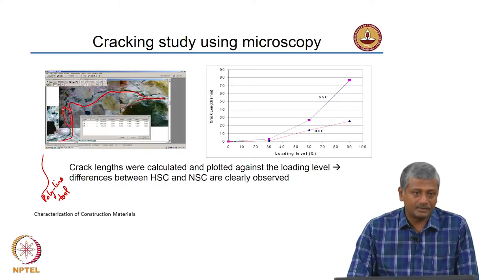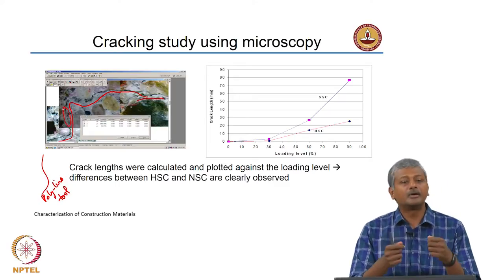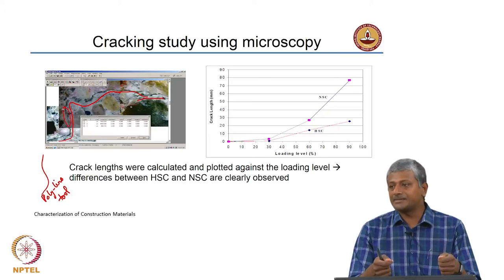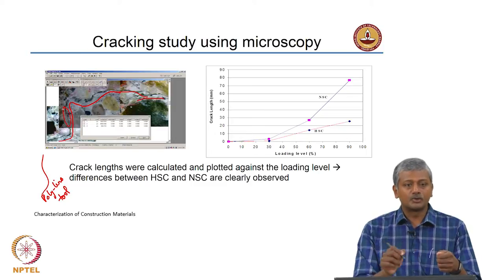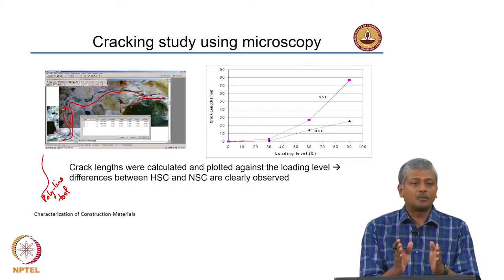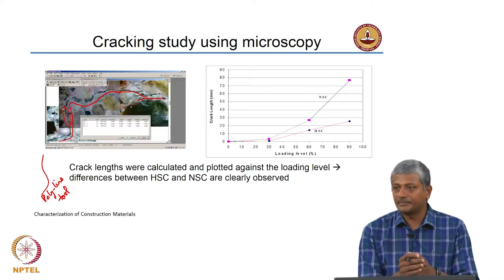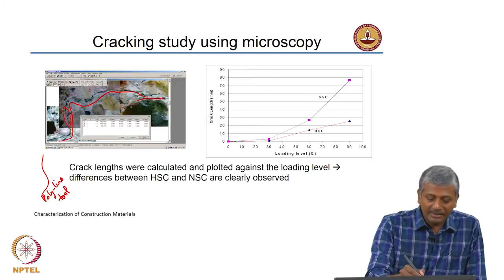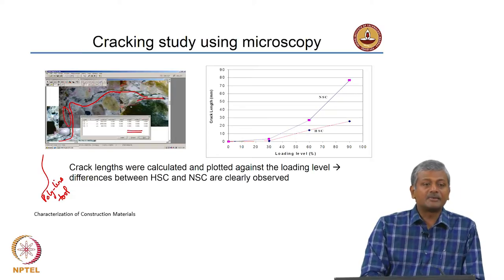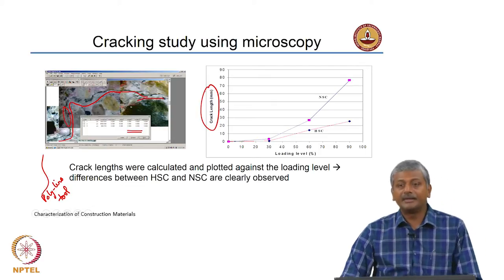We still have to calibrate that length. What was simply done was a ruler was taken and imaged at the same magnification. Then the polyline tool was used to trace a given length segment of the ruler. That gave us an idea about what length of the polyline tool corresponds to a specific length on the ruler, like 1 millimeter or 1 centimeter.